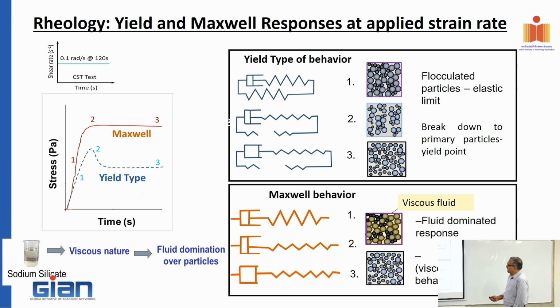This initial spring that you have here represents that percolated network that is giving that resistance. And once I shear it off, then it starts to flow, because suppose this spring were to break and I was to pull on it, what would happen? The viscous damper and the spring are the only two mechanisms giving me resistance. Primarily, the resistance is coming from the viscous part, right? So that is what we call a Maxwell model, typically of a viscoelastic solid, which flows if this spring were to break. And breaking of the spring is basically my peak here. That is the maximum resistance that I get.